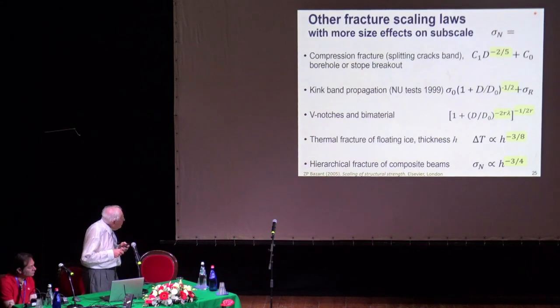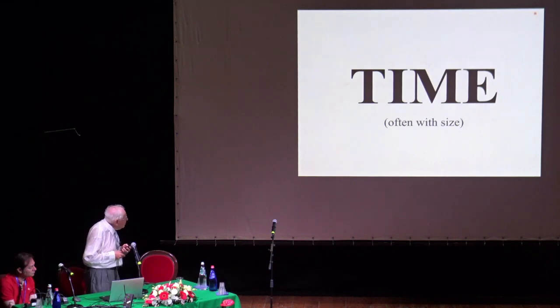V notches, of course, a different thing. Thermal fracture of floating ice. You cool the surface, the bottom of the plate is at 0 degrees C, and there is an eigenbending moment, and that leads to exponent minus 3/8. And in hierarchical fracture of composites, it has not been tested. You have a size effect in the failure of the studs, a size effect in the failure of the propagating line of the studs between the plate and the beam, and that theoretically should give minus 3/4, but has not been verified. It requires big testing.